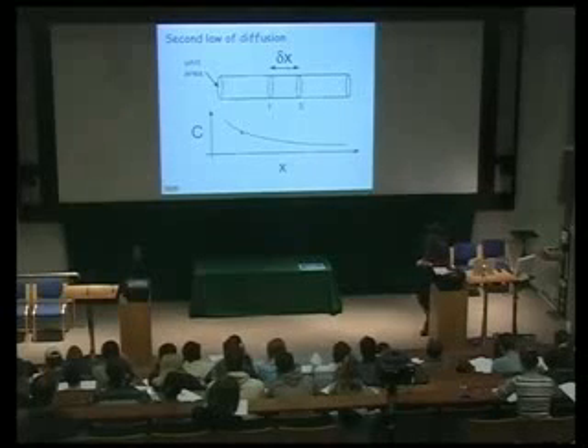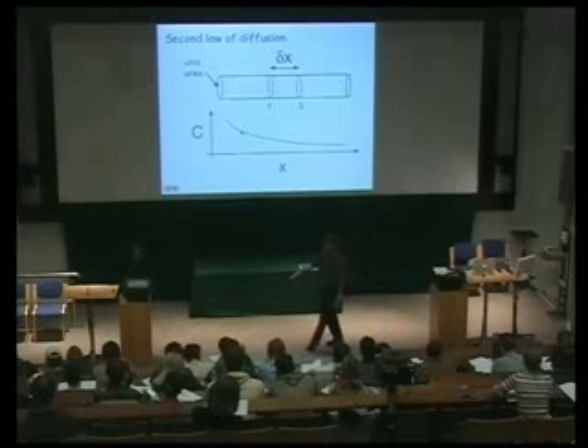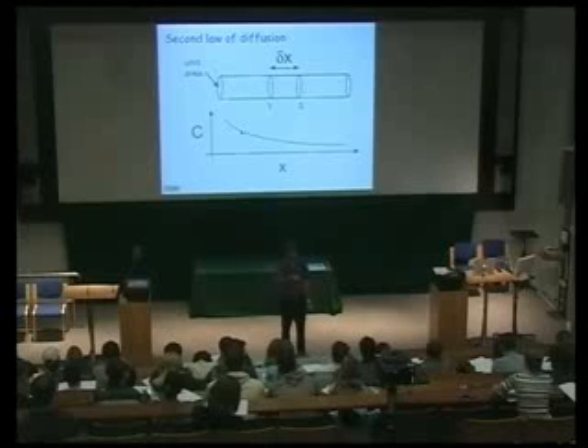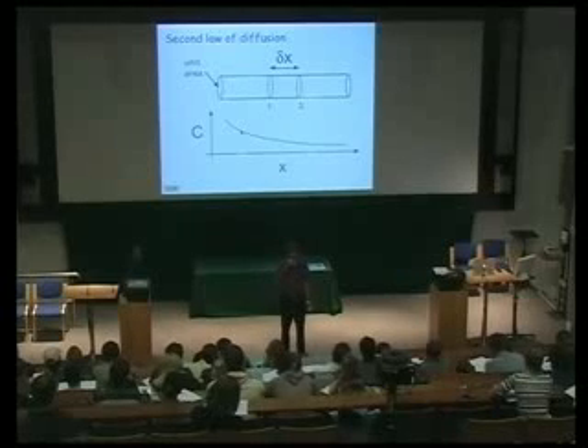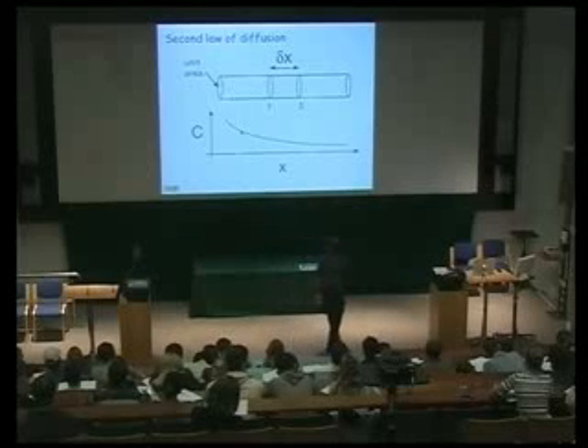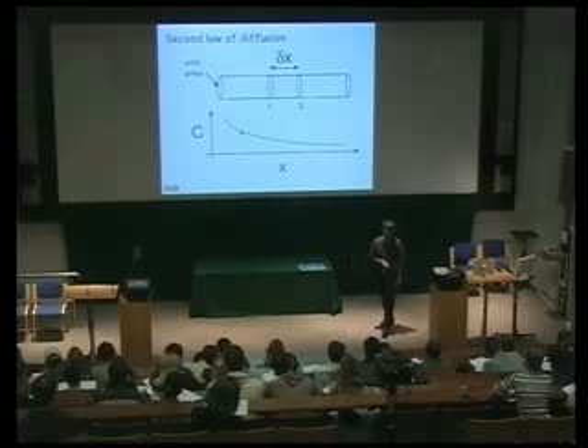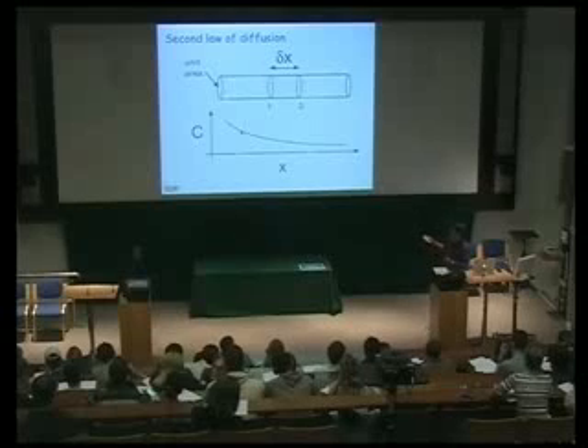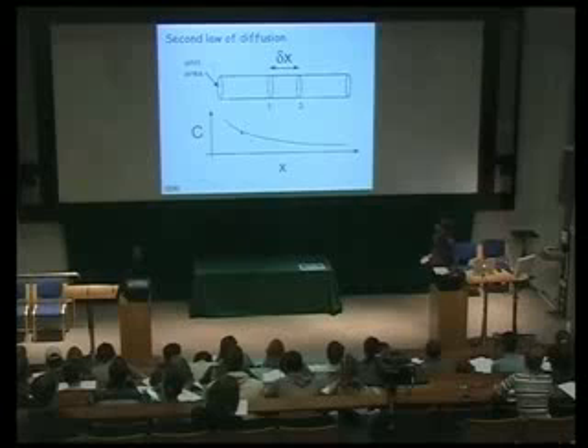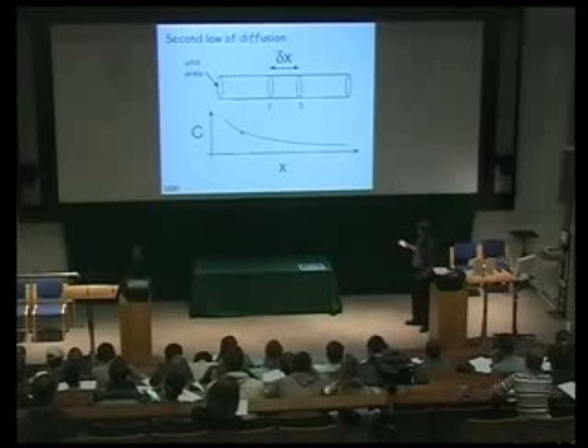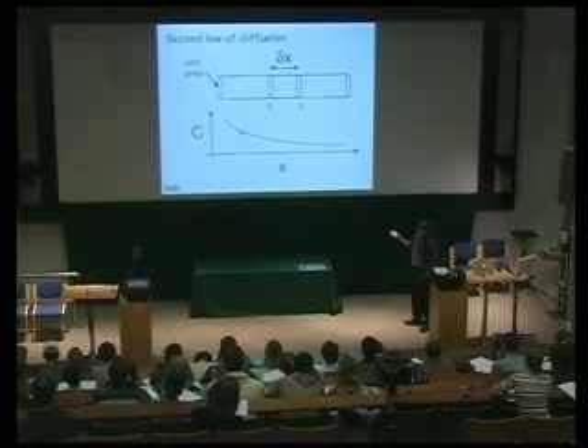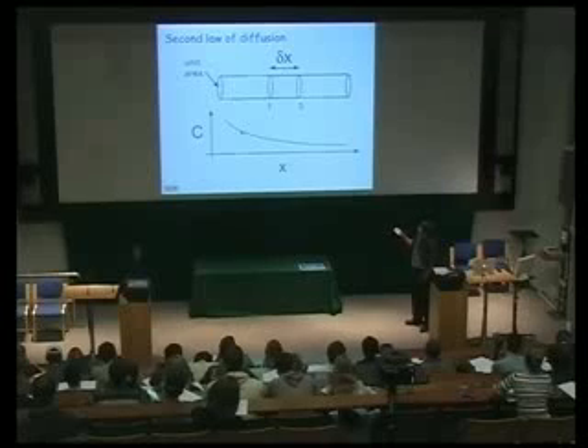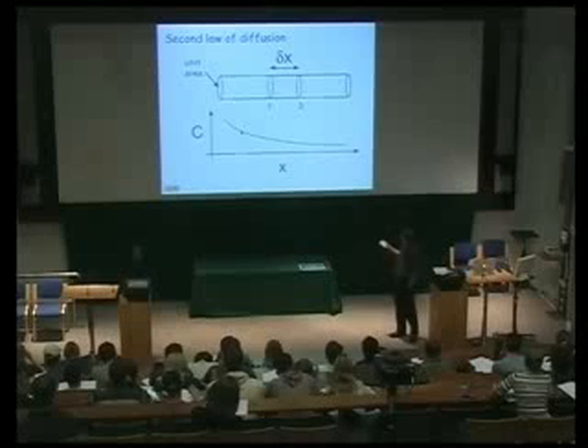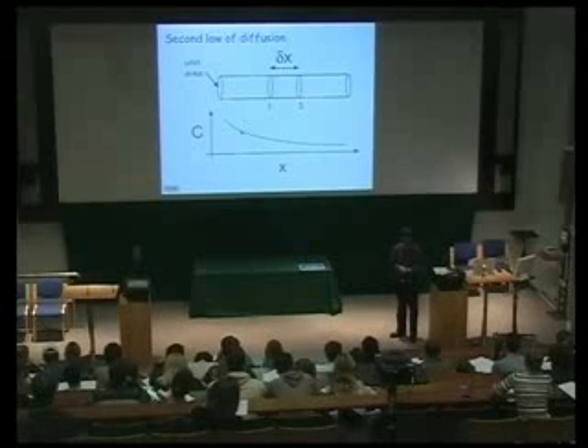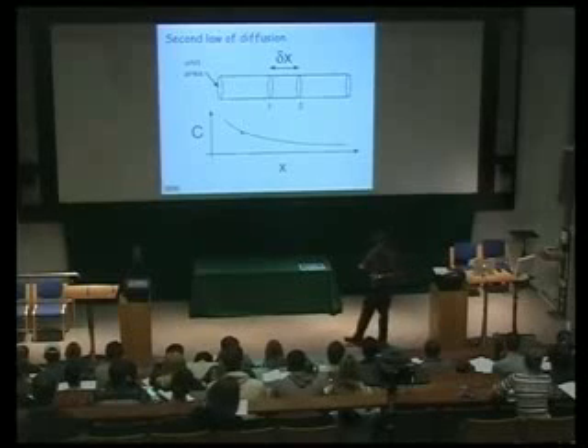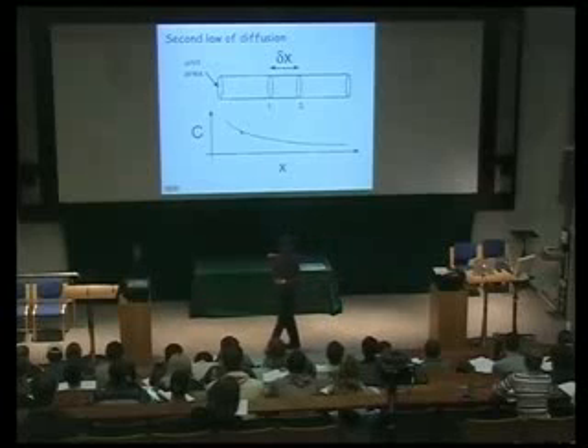Okay, now let's remove the approximation that the gradient is constant. See, in the previous analysis, the concentration varied with distance as a straight line. Okay? Now we are looking at a concentration variation which is not linear. So if I take the same bar and I look at two cross sections here, each of unit area, then the gradient here is different from the gradient here. So the flux crossing this plane 1 will be different from the flux leaving plane 2. So what will happen to the concentration in this region? Okay. The flux entering plane 1 is going to be different from the flux leaving plane 2.